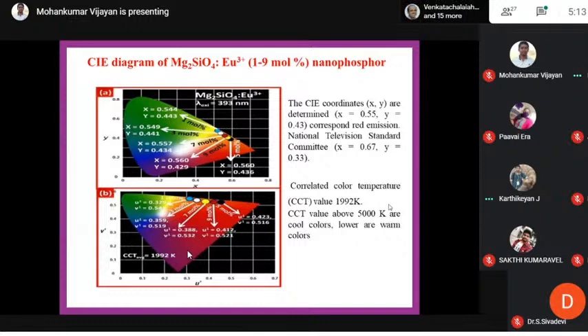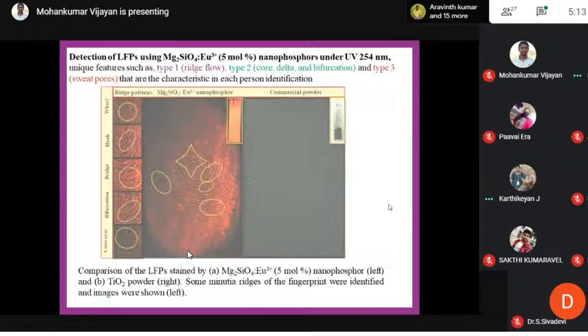So here from the CIE coordinates, the CCT temperature of our sample is around 1992 Kelvin. A CCT value around 5000 Kelvin is cool colors, and lower values are warm colors. Next. So these are the fingerprints we determined by using a latent fingerprint technique. So next.